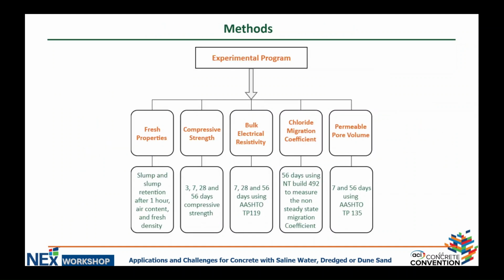For the testing, we did lots of different tests, including fresh properties. We measured slump and then slump retention after 60 minutes to see how produced water might affect the slump after 1 hour or 2 hours. We did compressive strength at 4 different ages: 3 days, 7 days, 28, and 56 days. And we also measured electrical resistivity. It might not be a good reflection of the durability of these mixes, but we did that to make comparisons between the produced water mixes themselves, because in that case it's going to be reliable.